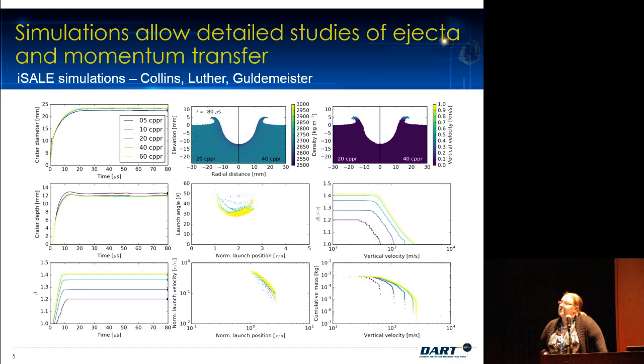So doing these sorts of simulations can tell us a lot of things. We can kind of pull out, not unlimited, but pretty much whatever we want from the codes. So this is an example of some information we've gotten from some of our European colleagues in the UK. And this is showing various things that they're looking at as a function of resolution of the simulation. And so you can see we can get crater size, so depth and diameter. We can get the beta factor, so how much momentum we are transferring to the body. And then various things about the ejecta, which are important if you're going to have some sort of either follow-on spacecraft or accompanying spacecraft to understand where the ejecta is going to be so it doesn't get sandblasted.